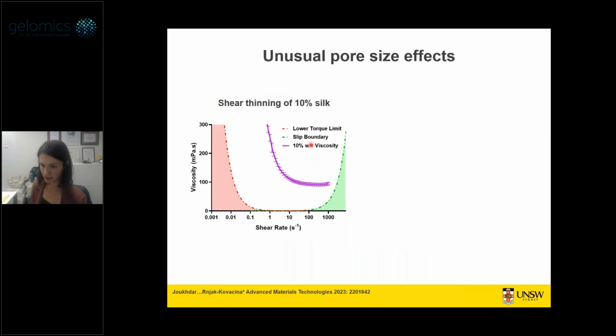So we started exploring what might be happening here, and we had this hypothesis that it's to do with the fact that 10% silk is actually quite viscous, and that silk is a shear thinning material. So if you increase shear on it, its viscosity reduces. And so we think when we were freezing at these uninsulated fast freezing conditions, the ice crystals growing through the silk were causing shear, and that was lowering the viscosity of silk, and that was allowing it to freeze in a sort of typical manner. Whereas once we slow down this freezing, there is less shear, silk remains viscous, and these ice crystals can keep displacing the polymer and growing. We modeled what those freezing conditions are and what the shear rates applied by the ice crystals might be, but it's still a difficult thing to prove.